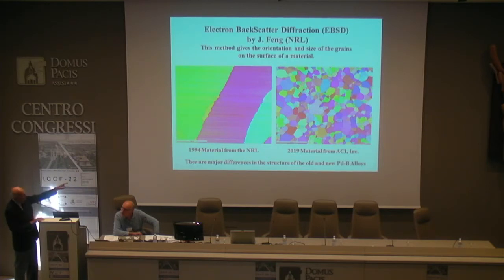So we could anneal in vacuum, or anneal in an argon atmosphere, the new material on the right to achieve something like that. So we have some considerable knowledge of what to do in that regard. But right out of the box, this is what we found with the materials. And mechanical working before annealing is important.